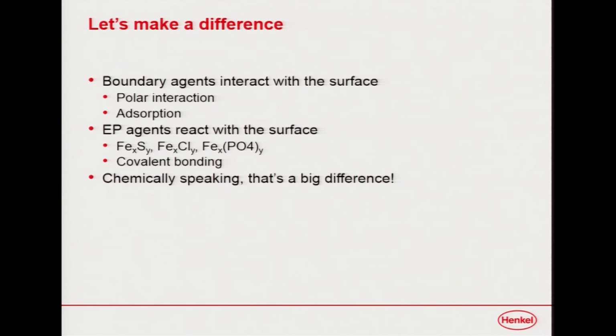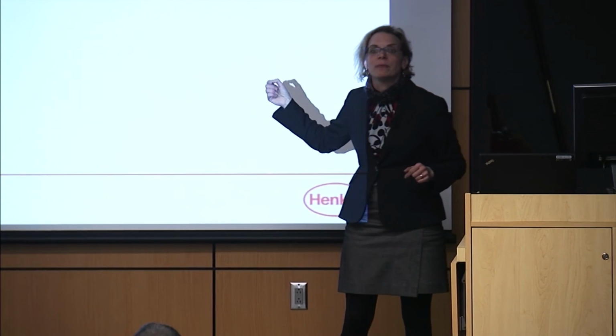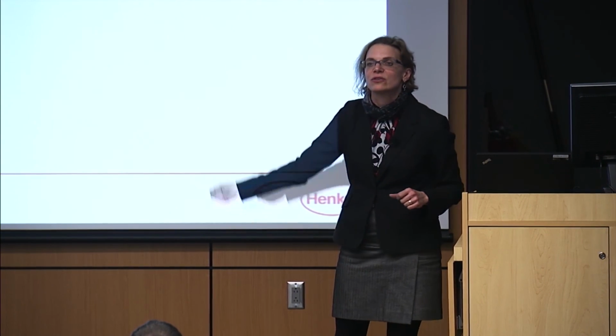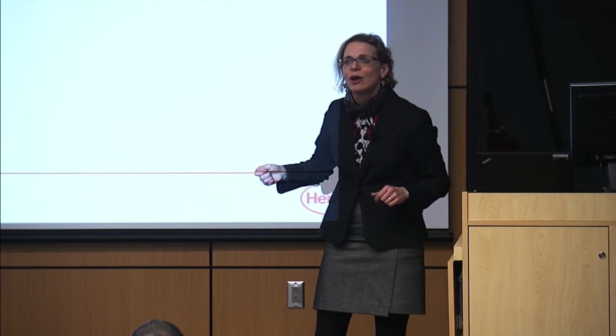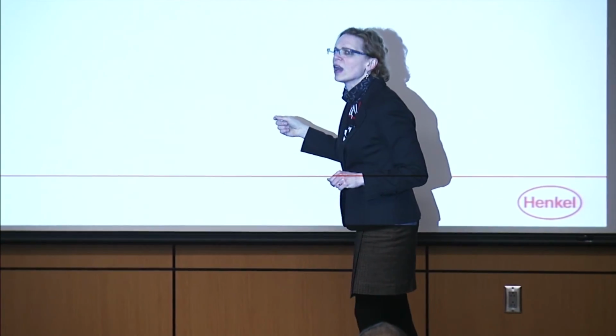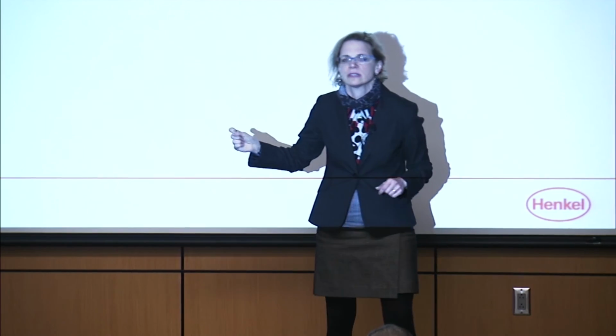I mean, they can. But what we decided, or what I looked at, was, is there a difference between materials that absorb to the surface and materials that covalently bond? And actually, you form covalent bonds. So if you're an inorganic chemist, you can start making salts, but you can also make salts that flow. It's a big difference to go from a very, very basic polar interaction that's very weak. It doesn't take a whole lot to rip those oleic acids or those fatty acids off the metal or metal oxide surface. But you really have trouble to undo iron sulfide. This is a challenge. This is a lot of energy if you want to take that apart.